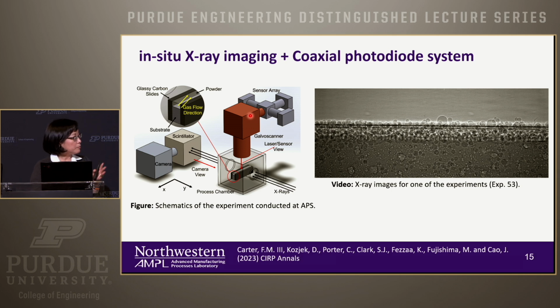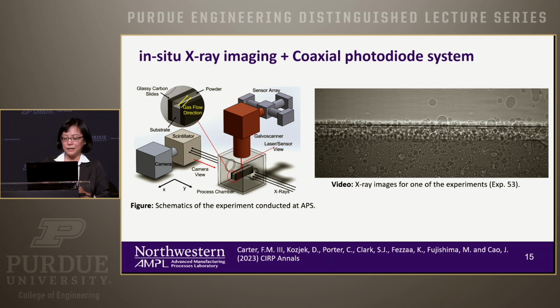We put them together because this system you can install on traditional or commercial machines, right? So if we can have a good correlation between the ground truth that we learned from APS and the photodiode system, then we can transfer this knowledge to very large parts in different areas. So with that intention, we went to APS, and you can see here, as the laser goes from right to left, you see the melt pool over here.